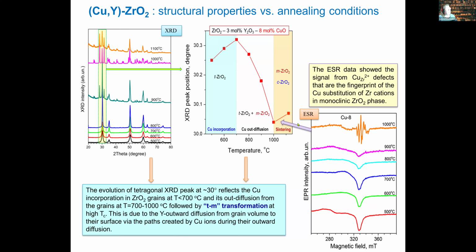And if we look at the electron paramagnetic resonance, we got information about first the formation of copper oxide entities on the surface of zirconia grains, then its incorporation, with a decrease in this intensity as copper goes inside the volume of zirconia grains, and at higher temperatures we see a dramatic transformation of the signal. This signal exactly corresponds to formation of copper on the zirconium site, and these defects appear only in the monoclinic zirconia phase. So if we have such defects in our materials doped with copper, we definitely know that we have monoclinic phase.